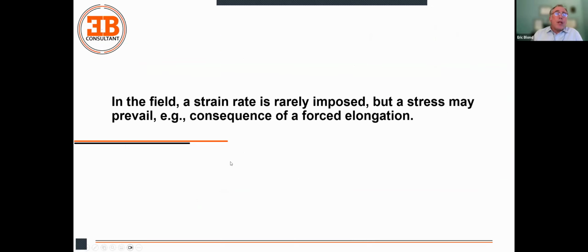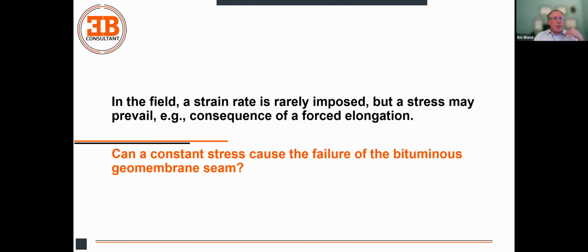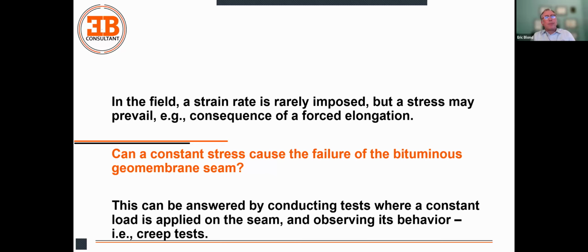So in the field, such a strain rate is not something that can really happen. What's happening in the field is a forced elongation, and therefore it's going to be a stress. So the question we had next is, can a constant stress cause the failure of the bitumen seam? This can be answered by conducting tests where a constant load is applied on the seam and observing the behavior with a creep test.